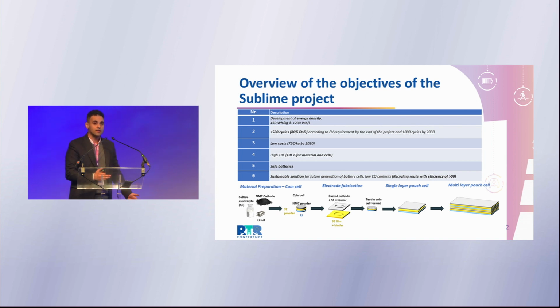Cyclability, so the cells should have a very good cycling stability of more than 500 cycles. Then, of course, the low cost. So in this project, we calculated that the cost of the cells could be down to 75 euros per kilowatt hour if the cost of the solid electrolyte is below 50 euros per kilogram.